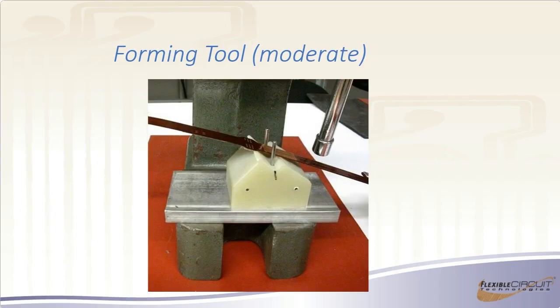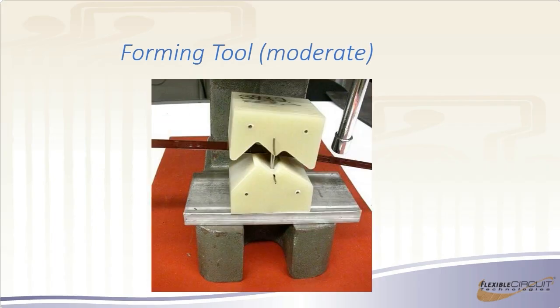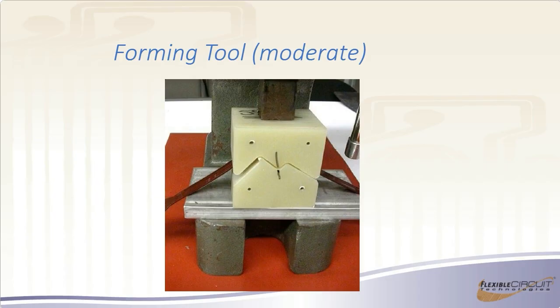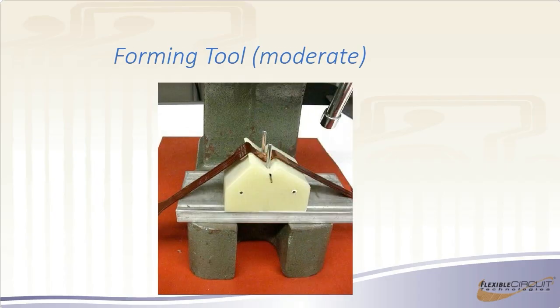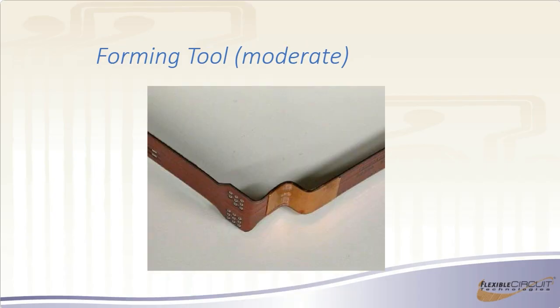This is a little bit more elaborate one. We needed 2 bends that had to be exactly spaced apart a certain amount. And so this was basically just a piece of machined FR4. It could also be a 3D printed block that was put into that same arbor press with a mating cavity, and it was forced down. And we had actually added copper to the outside just to give it a little bit more memory. So when we formed it, it wouldn't relax at all.